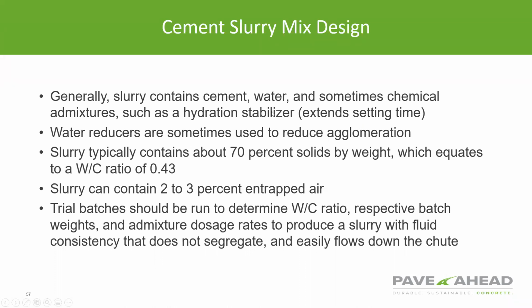And so just some general comments about the slurries. Of course, they contain cement, water, sometimes chemical admixtures such as a hydration stabilizer that extends the set time. Sometimes water reducers are used. Typically, slurries contain about 70% solids. Remember that the Illinois DOT spec requires 50. So the 70 equates to a water cement ratio of about 0.43.